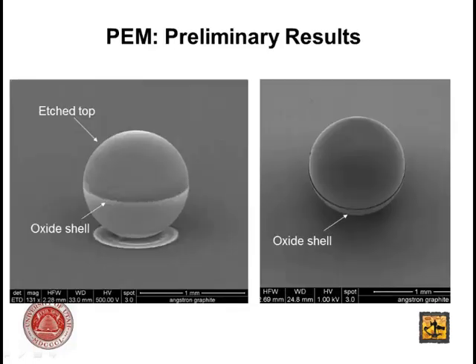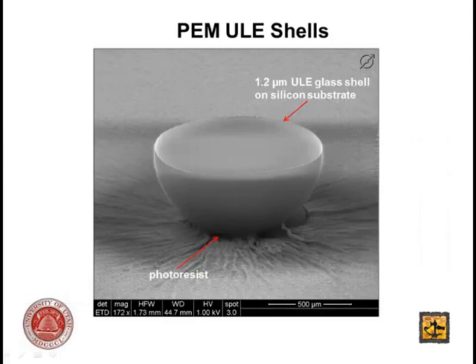Okay. But if you complete the etch, this is the kind of thing that you get. You get an oxide shell, and then the etch to the top. And then if you do a sacrificial layer, you can end up with a gap. And after you remove them all, you get structures that look like this. So this is like a half sphere made out of this ULE material.